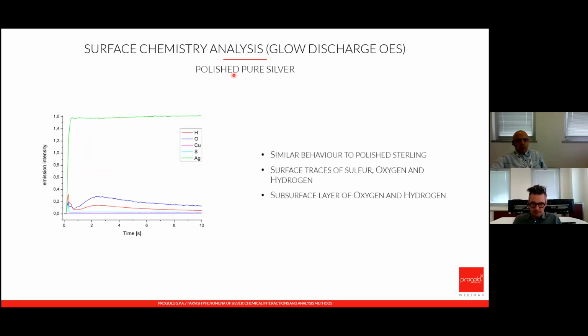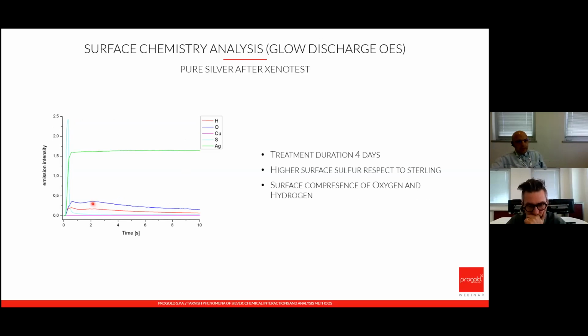Pass now to the pure silver. Its behavior produced results similar to sterling silver, with traces of sulfur, oxygen, and hydrogen on the surface, and some oxygen and hydrogen from the manufacturing process in the underneath layers. Similarly to sterling silver, but to a higher extent, pure silver developed a strong concentration of surface sulfur under ultraviolet radiation. And once again, the presence of oxygen and hydrogen traces on the surface proves the important key role of humidity in this passivation process.